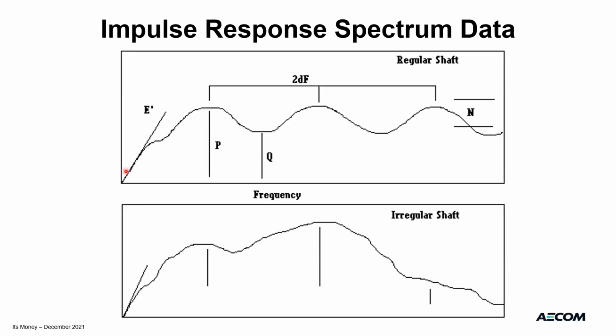The slope at the beginning of the curve helps us calculate the dynamic stiffness of the pile soil complex. Resonant peaks are generated by the reflection from the base. So the spacing between those enables us to calculate the depth that the reflections come from. The P to Q values here, the peak and trough values, are a function of the side friction on the shaft, of the damping of the shaft. And the location of the first peak relative to the origin, the phase of the signal, helps us to determine approximately how much of the bearing capacity is generated in end bearing and how much is in side friction.